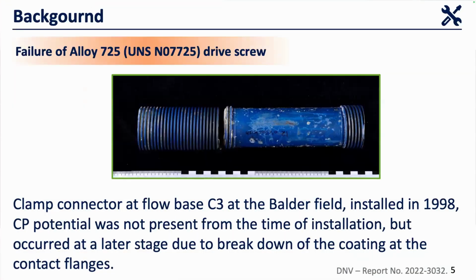Another case reported in 2022 is a clamped connector at the flow base C3 at the Balder field. It was installed in 1998, and it has been in operation for more than 20 years. And after that, a failure was reported on this alloy. It's an alloy 725 drive screw. The cathodic protection potential was not present at the beginning, but after some time, there was a breakage of the coating on the surface, and then the material was directly in contact with the CP condition. And finally, this fracture happened.